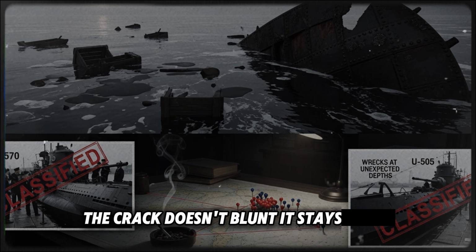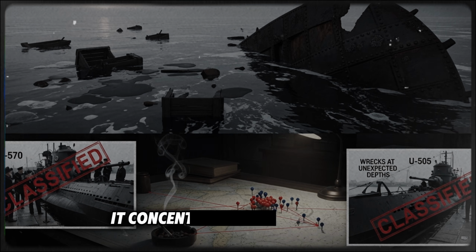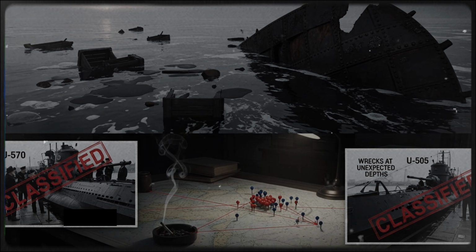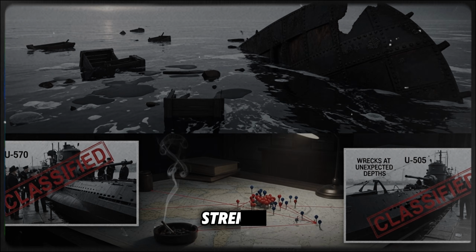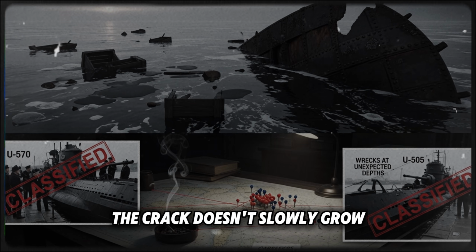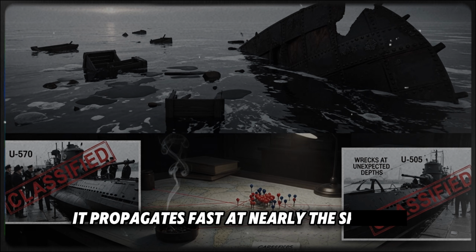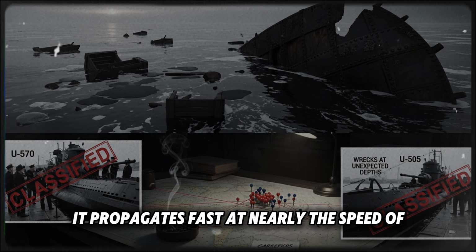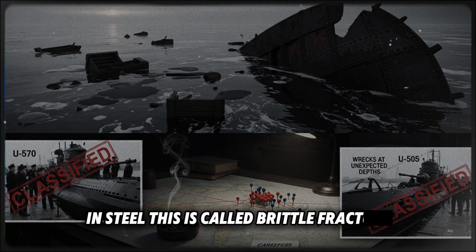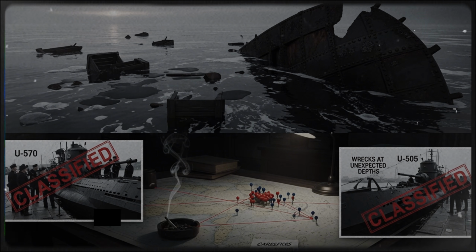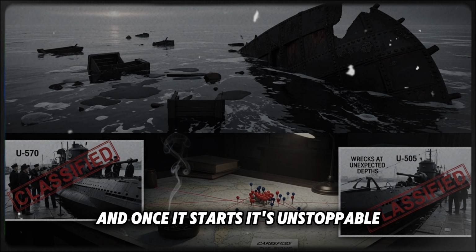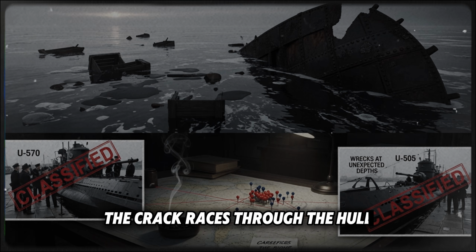But in brittle steel, something different happens. The crack doesn't blunt, it stays sharp. It concentrates stress at its tip, and when the stress exceeds the material's strength, the crack doesn't slowly grow. It propagates, fast, at nearly the speed of sound in steel. This is called brittle fracture. And once it starts, it's unstoppable. The crack races through the hull.